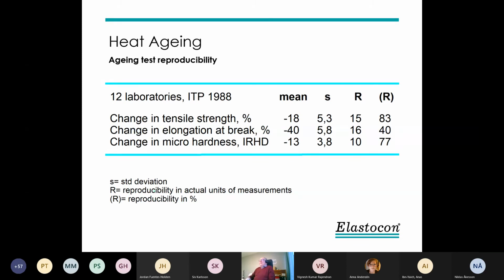The most important property when you check aging is in fact the elongation at break, because that always goes down and will be lower with aging. That was reduced 40% with an absolute R of 16%, and the percentage between these two is 40%. If we look at micro hardness, IRHD, the hardness went down 13 degrees, and the R is 10 hardness degrees